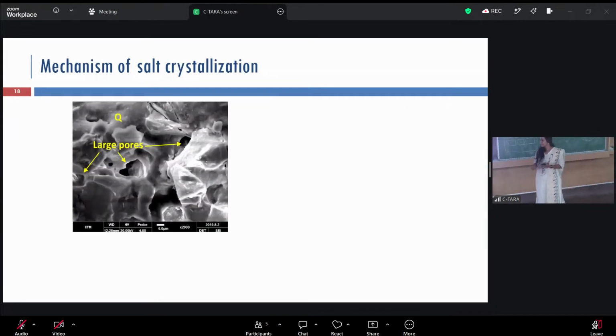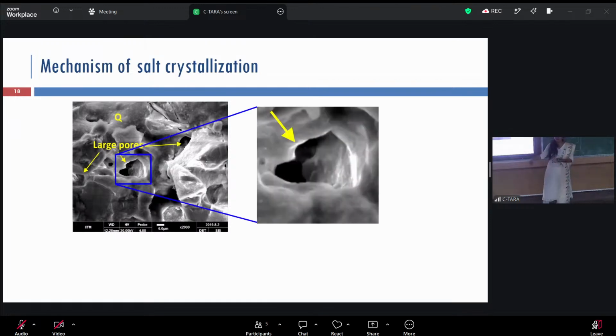Now, the mechanism of salt crystallization is, if you're having pores in a system, this is a scanning electron microscopic image of one of the samples. If you have pores in the system, salt water will get in. Subsequent dry wet cycling, the concentration will increase, salt will precipitate. If it grows, if it has space to grow, it's absolutely fine. But if it doesn't have space to grow, it will exert pressure and crack the material, and the material will fail eventually.